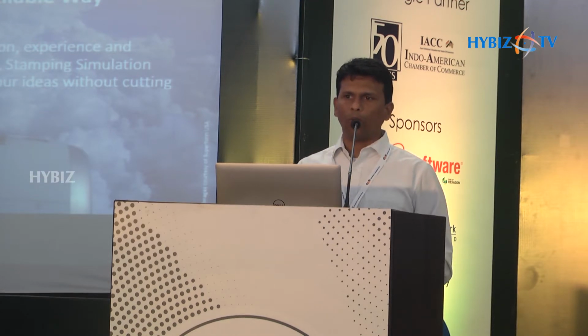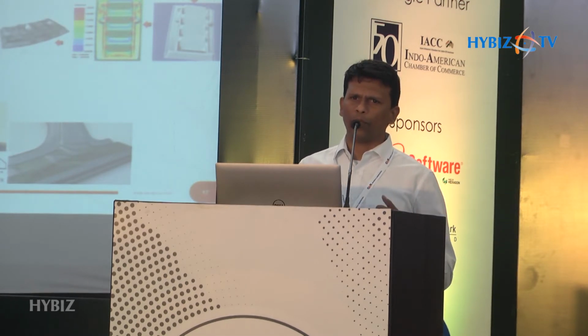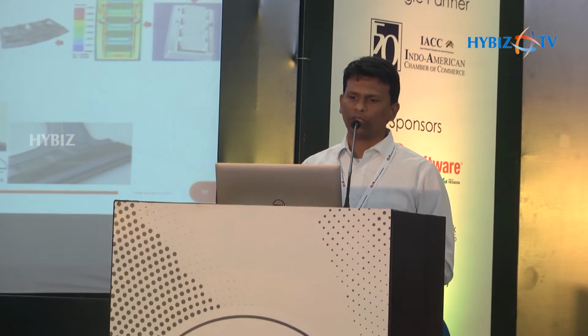I move into the next solution, which is the metal forming solution. We have various aluminum and titanium materials that are basically formed using the metal forming process. There are many challenges associated with aluminum material with respect to titanium material, with respect to high tensile material, high strength steel, and again I come back to the garbage in, garbage out statement, where you need to have a very good understanding of what your material behavior is. If you don't understand what your material behavior is, you will not be able to later predict your defects at all. So what happens in material prediction is basically the availability of the material, and the test that is associated to that is very limited, or very expensive if you want to do that.